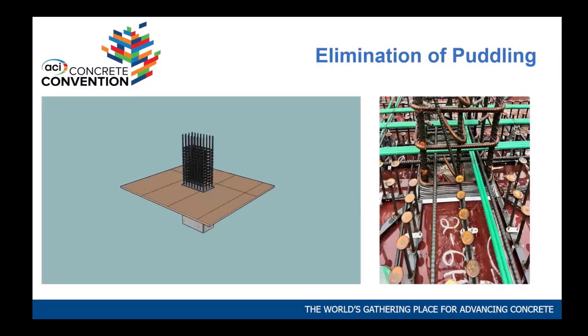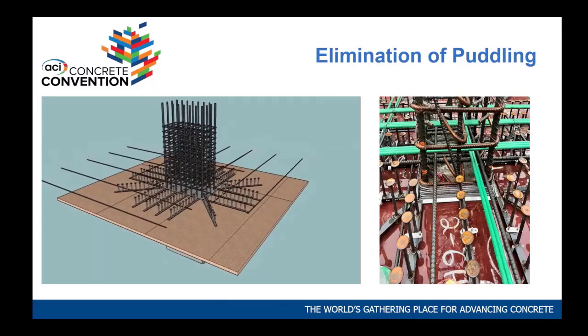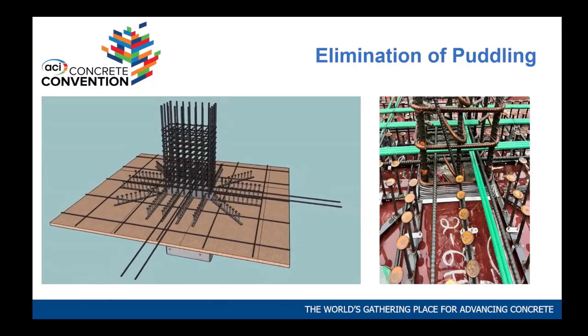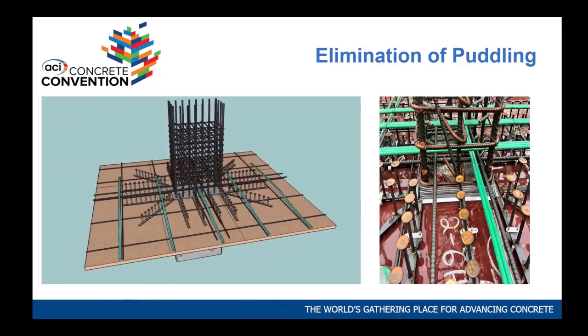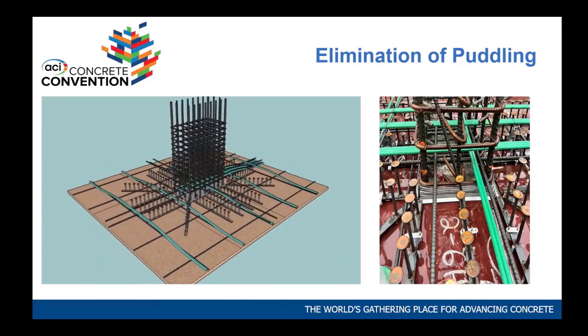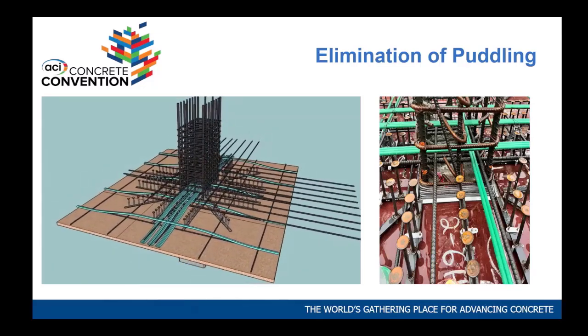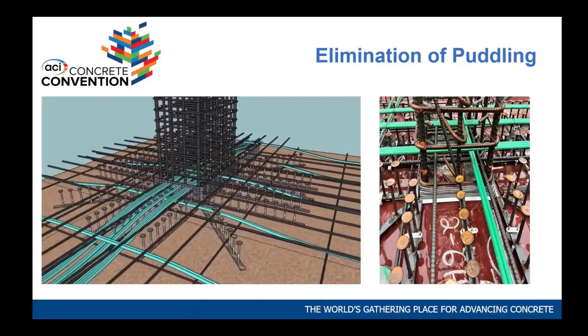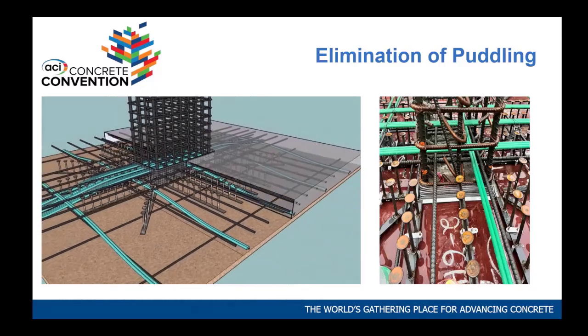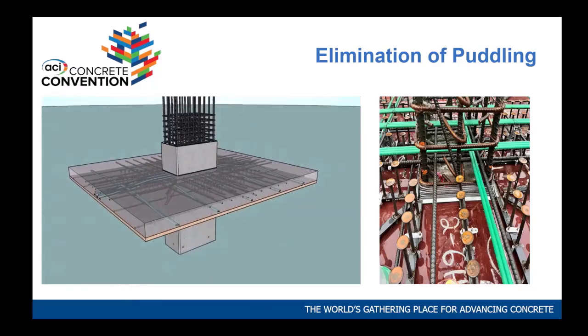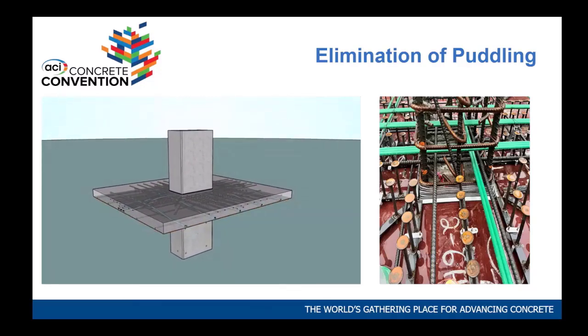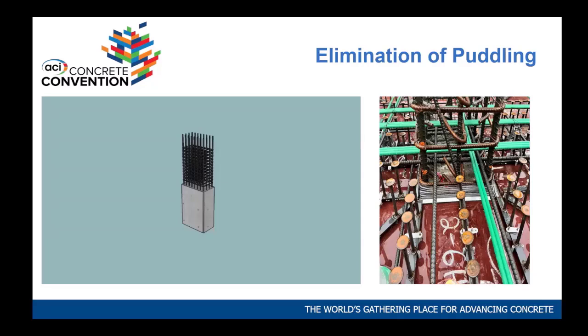So you could see it again, and then avoids the puddling. The trick was usually to put the stay form, but what they did here, they put that stay form first. You have to make sure you put the shear steel bars so that on top of the friction between the concrete, you have shear steel that passes to, it's like a midpoint bar that goes into that joint. And then they put stay form again up here after they put the top bars, and they pour it. Much easier than putting 2 mixes, try to intermix them, so on and so forth.